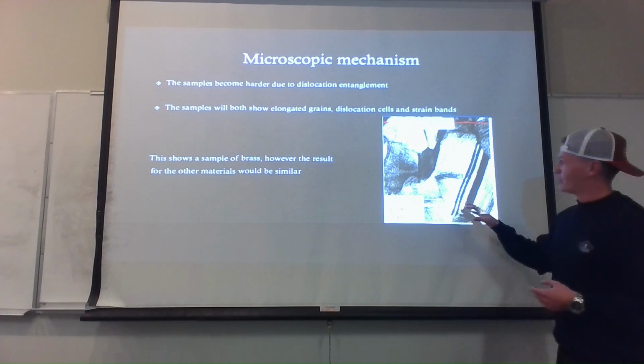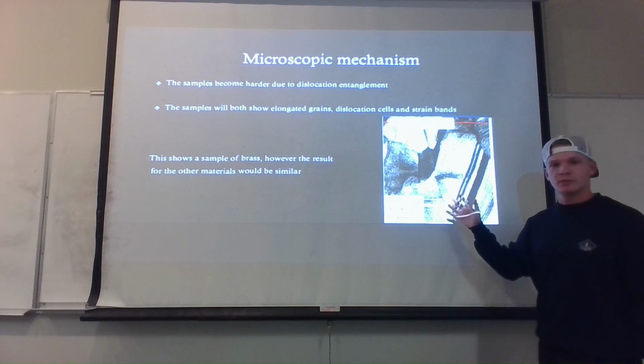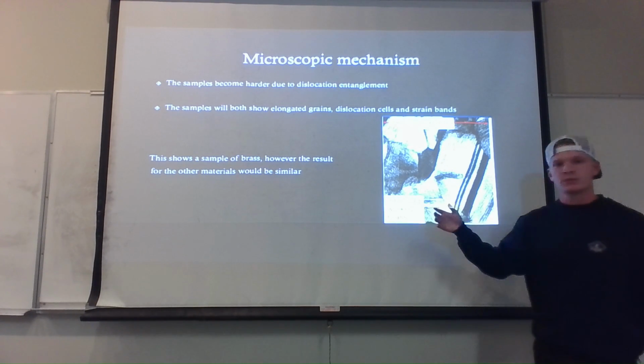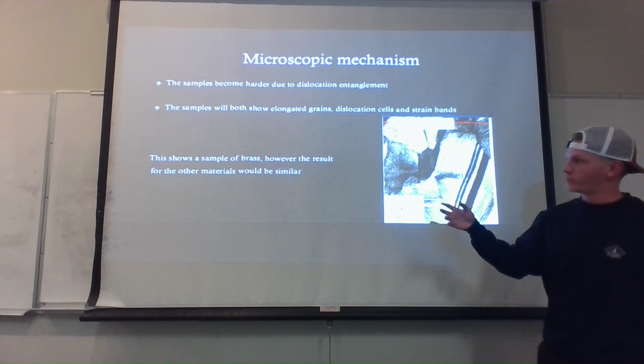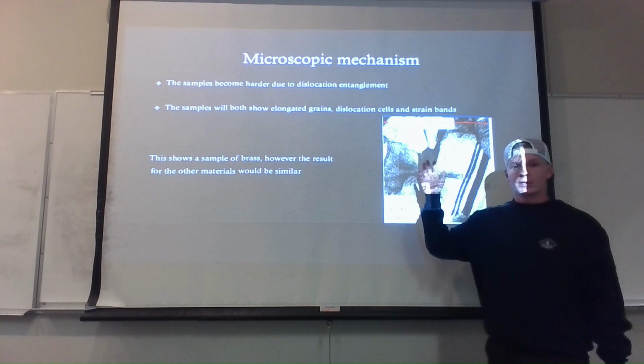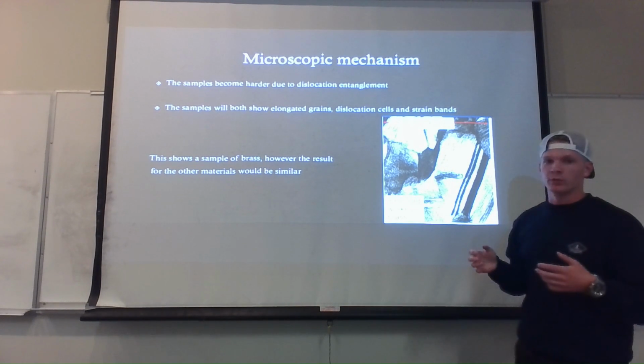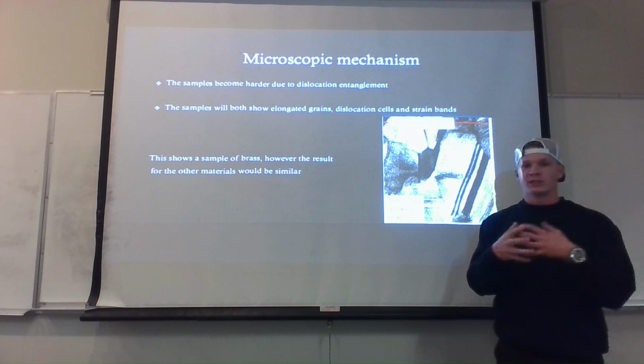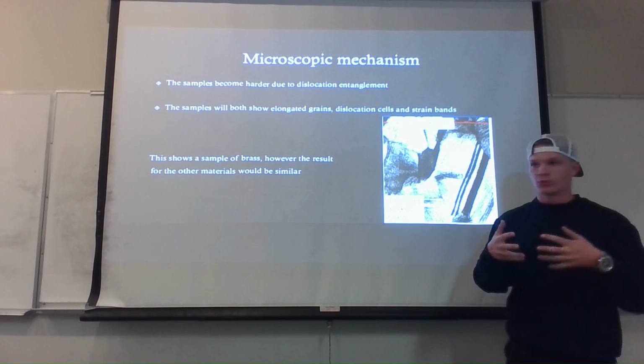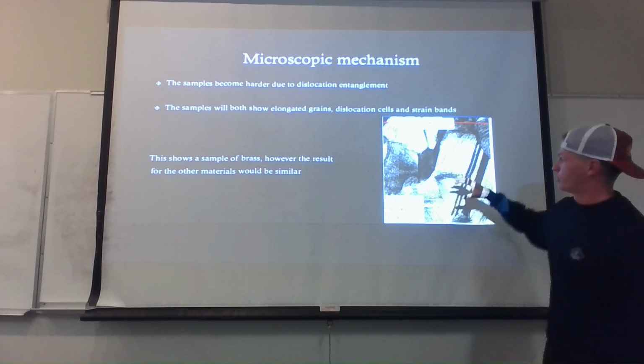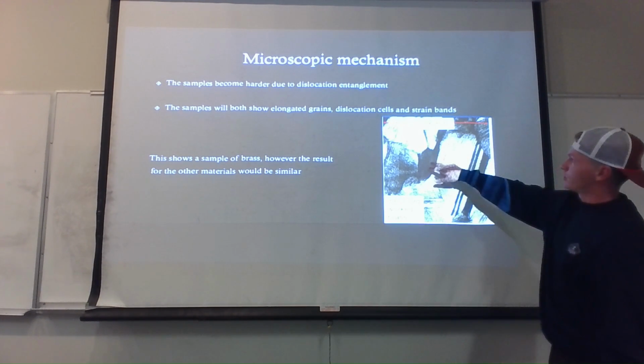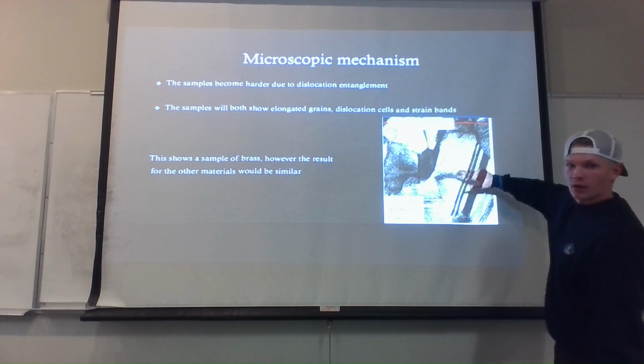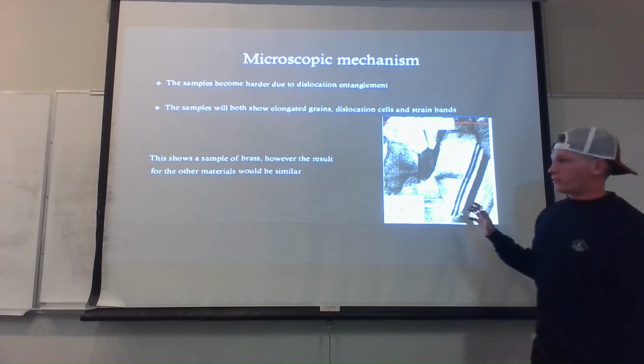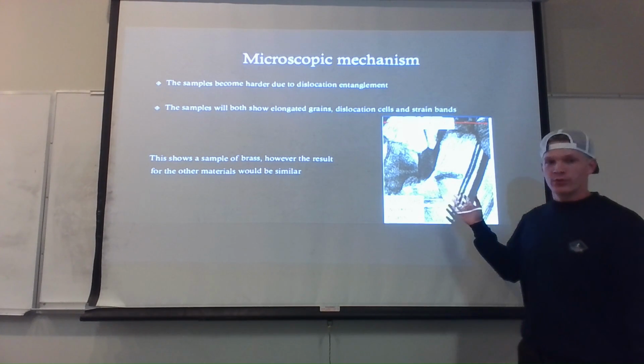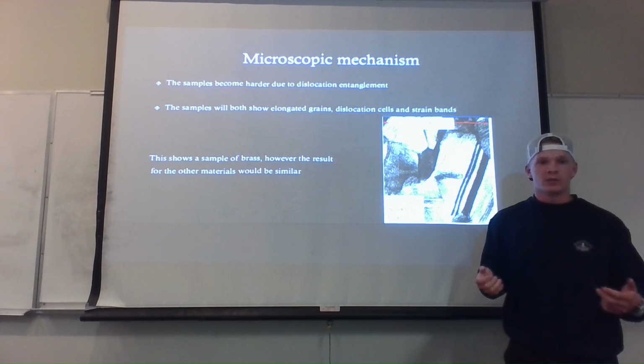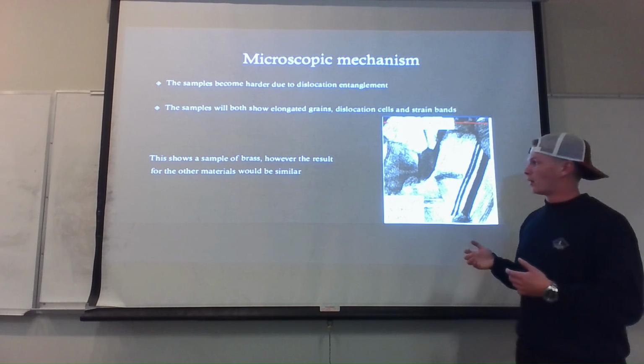So this picture here, it's a little hard to see, but it's showing the different grain sizes. This is a sample of brass, but it's the same idea that you would get from the other materials. So the samples are becoming harder because of dislocation entanglement. So all those dislocations happening in the material are entangling with each other and making it harder for the material to break. The samples will both show elongated grains, dislocation cells, and then there's also going to be strain bands like these here. So that's just showing that while this isn't the samples we used, that's what's happening when you cold work a material, and that's going to be what's making them stronger.